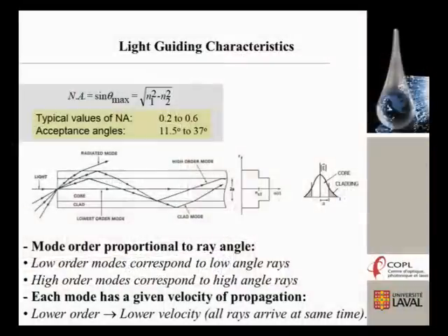Normally the numerical aperture is a very easy equation that we will use. Remember, you can derive this from the first equation, and we got this sine theta maximum of light that we got inside the fiber, and this is the square root of n1 squared minus n2 squared. The typical value for the silica fiber is between 0.2 to 0.6, which gave us an average angle between 11 to 37 degrees, maximum 37.